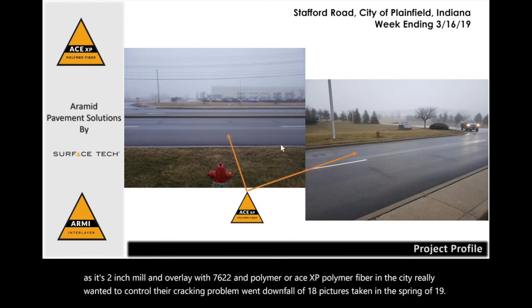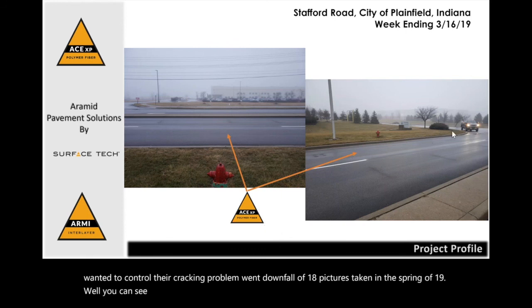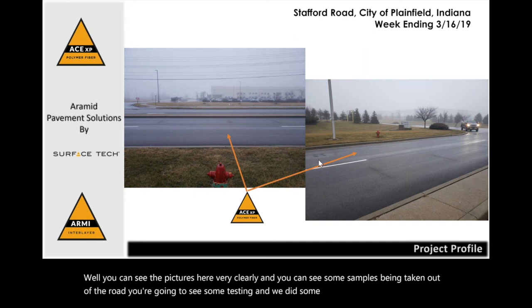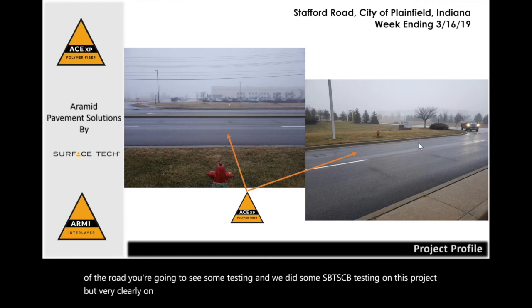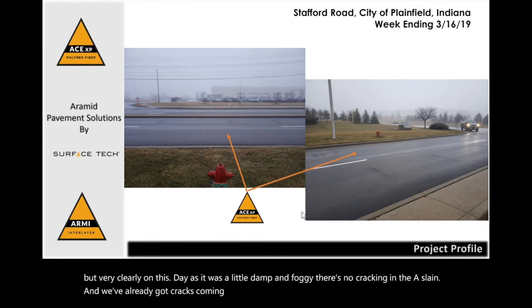Well, you can see the pictures here very clearly, and you can see some samples being taken out of the road. You're going to see some testing. We did some SCB testing on this project. But very clearly on this day, as it was a little damp and foggy, there's no cracking in the ACE lane. And we've already got cracks coming back at every one of those joints that was underneath.